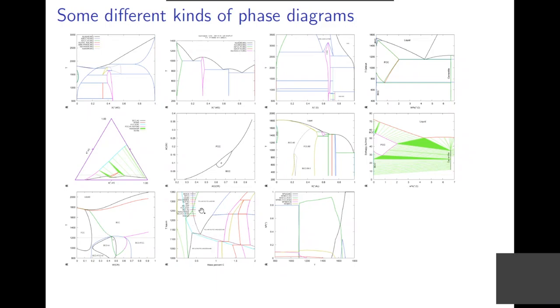This is also a phase diagram for a multi-component high-speed steel. So you have different carbides forming at different temperatures and you have invariants. And here it's useful to combine a phase diagram with the step calculation. Here I have the same material, but I have fixed the carbon content and varied the temperature. So one can see how the amount of phases changes with the temperature. So this is a kind of overall impression, and then you can select more detail where you want to do more calculations to obtain more exact information.